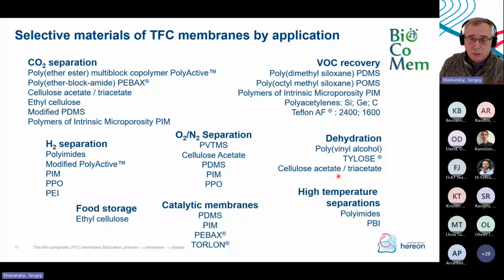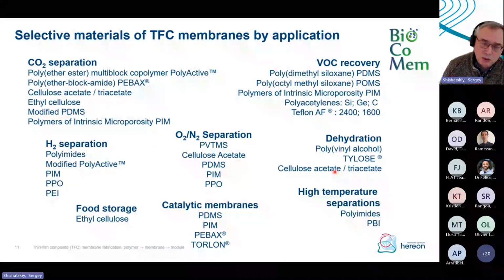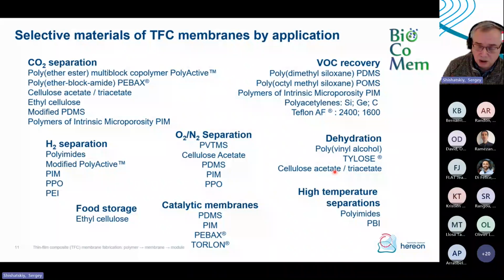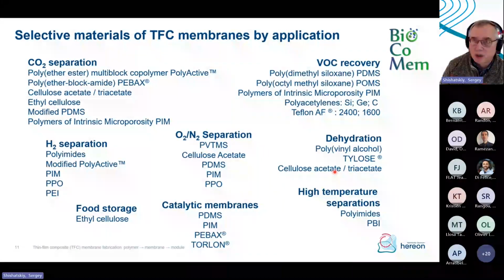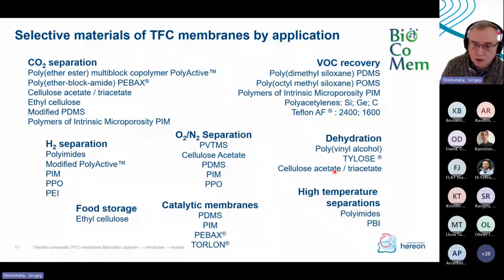Since we have a very small amount of polymer deposited on a porous support, we can use basically any material which forms a film. Here you can see the variety of applications for which we are using our thin film composite membranes with different selective layers. It can be a glassy polymer, it can be a rubbery polymer. Actually, we do mixed matrix membranes. We make immobilized ionic liquid membranes. So everything.